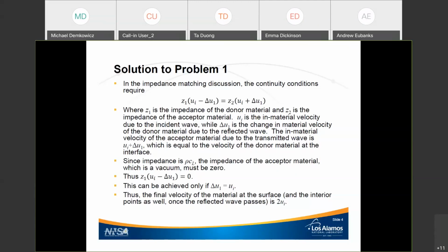It causes the atoms to displace, but then those apply a force, because the potential wells in which adjacent atoms sit have been distorted. And so those atoms are forced to move, and then they force the atoms adjacent to them to move, and so forth and so on. So you get this disturbance that propagates. This is the same thing. It's just that the force, if you will, that is applied at the surface was due to the arriving wave, and because the atoms at the surface, if you think about it, the potential well they are sitting in is only half as deep as the potential wells of the atoms in the interior.